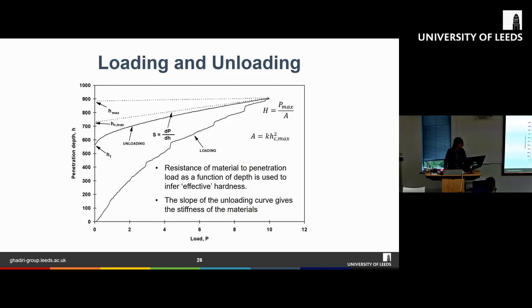Essentially, when the indenter first starts coming into contact with the surface of the material, you can see that the load starts increasing up to a maximum point that you specify, and then it will start unloading. But it won't unload back to the original line, so there's some sort of hysteresis here, and that's due to the plastic deformation. And what we see here, around this point.